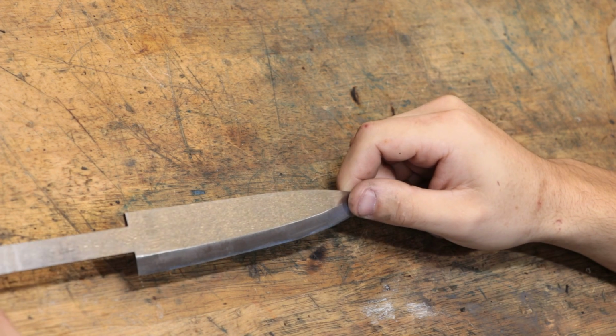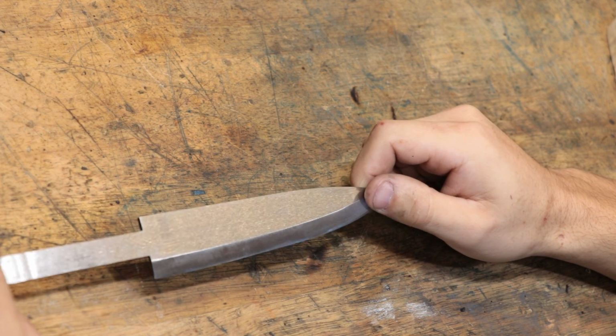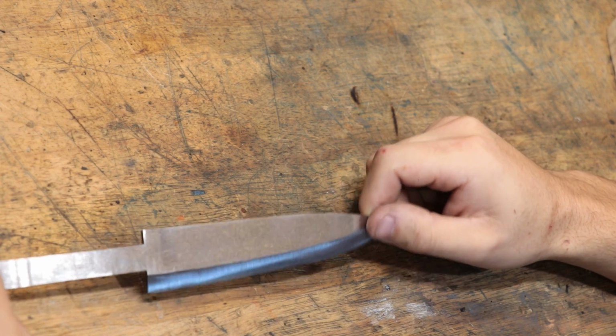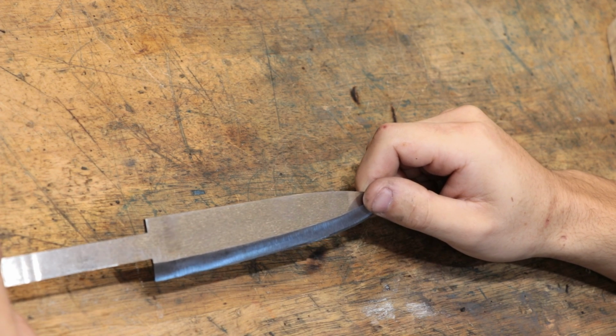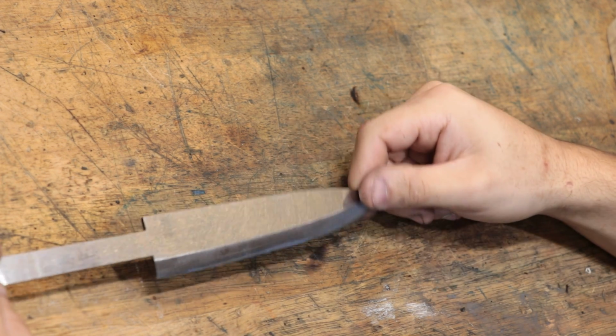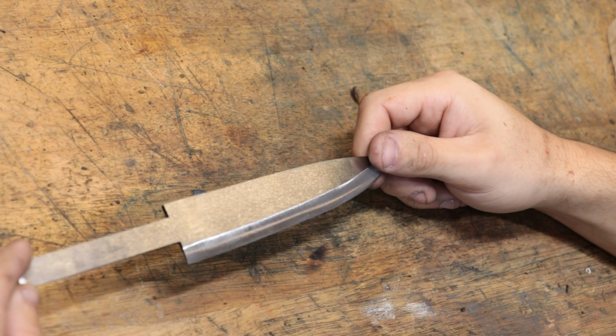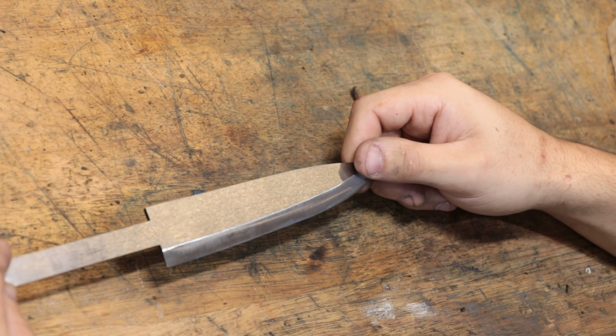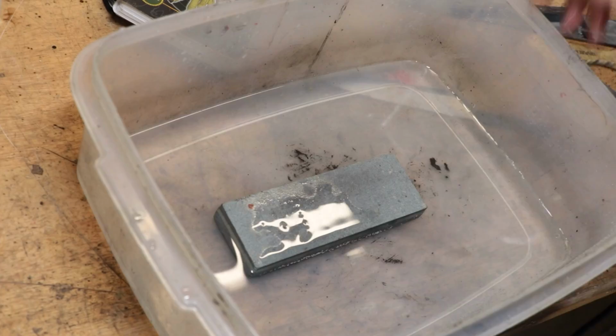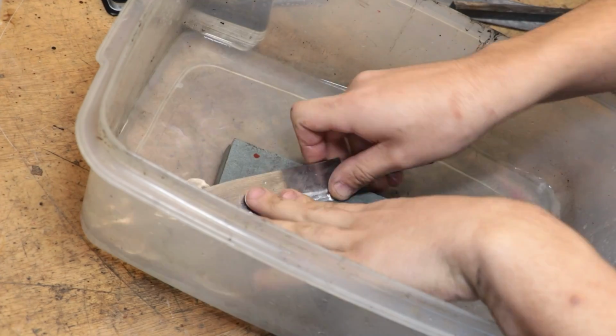Now the next step is to reduce that brittleness and get some of that toughness back, and that's going to be the temper step. Sometimes I do skip tempering with case hardened parts, but since the blade has probably hardened all the way through, I am going to have to temper it. In fact, just to show you how bad it was, I tried to sharpen it on a whetstone and the edge kept chipping.